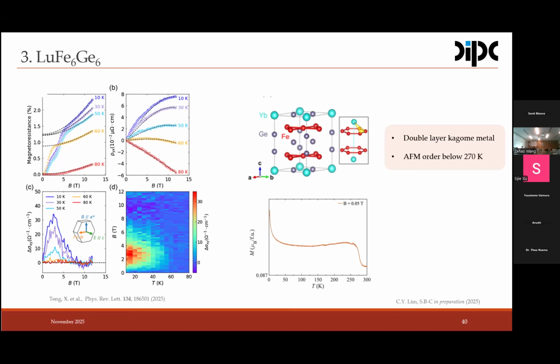And the second motivation for this work, actually, I am always following up what you guys do here at RISE, is this paper recently published in PRL a few months ago, I think, where the group of Pen Cheng measured the anomalous Hall effect in the ytterbium iron 6 germanium 6 sample. So I tried to measure the ytterbium sample. Didn't click, so it was a kind of a rock, but we came up with the lutetium one, which actually has the same structure. Double layer Kagome plane like in the scandium vanadium 6 germanium 6.